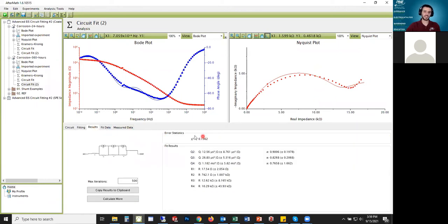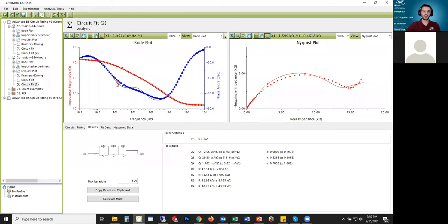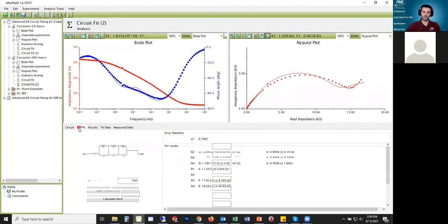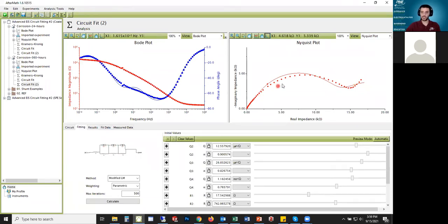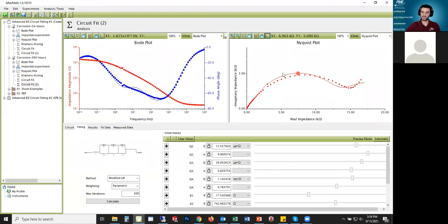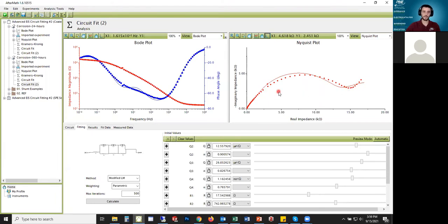You can see this fit isn't terrible. The phase angle kind of goes under, then over, then under. The impedance magnitude actually looks quite good, but the Nyquist plot really kind of doesn't. There's just some kind of qualitative analysis that you do when circuit fitting. If you think this is really what's going on, that there's nothing exposed, it's fully covered still, you just go with this fit and get the parameters you want. I'm not satisfied personally with this. This doesn't really fit the Nyquist plot as well as I would like.